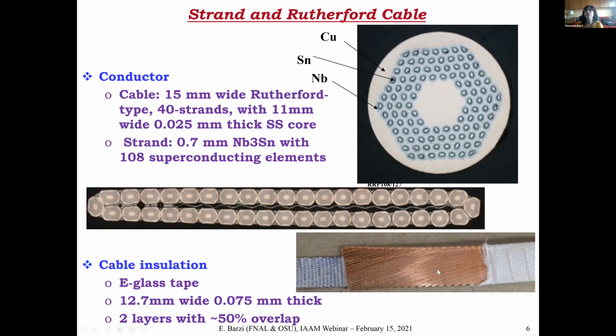And this is the cable from top with its insulation, and the insulation is a ceramic, it's glass, so we use ceramic a lot. And then you have to heat treat this cable. First you wind your coil, and then you heat treat the whole coil, and that's where the diffusion of the tin occurs. So the tin diffuses into the niobium filaments and forms the stoichiometric compound niobium-3 tin. So it's a very complex system.